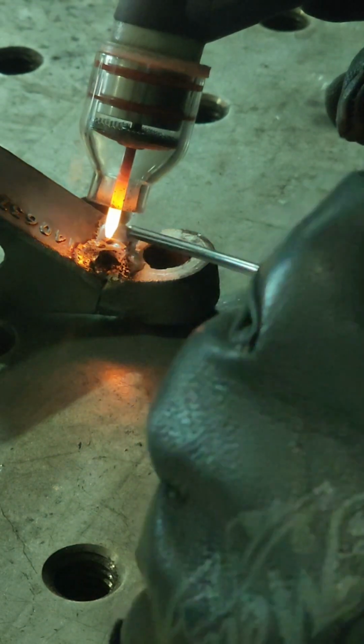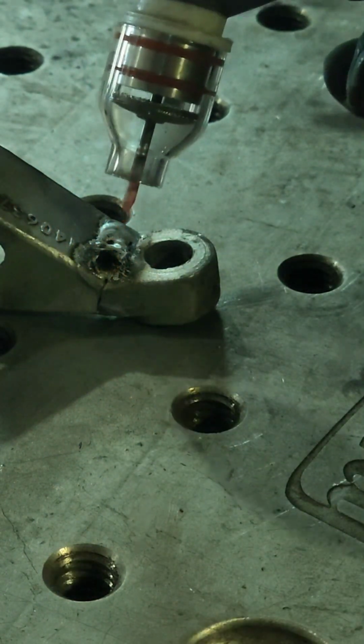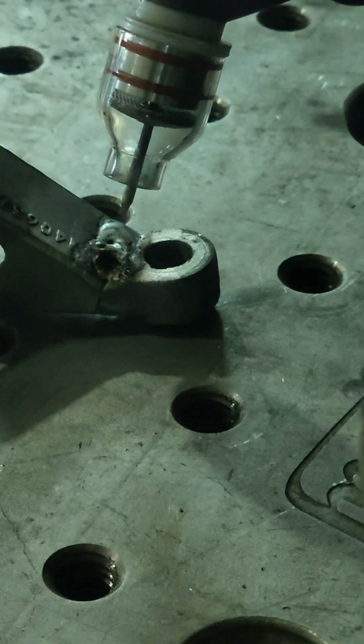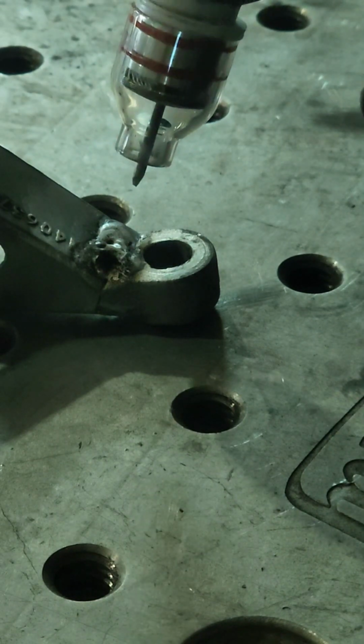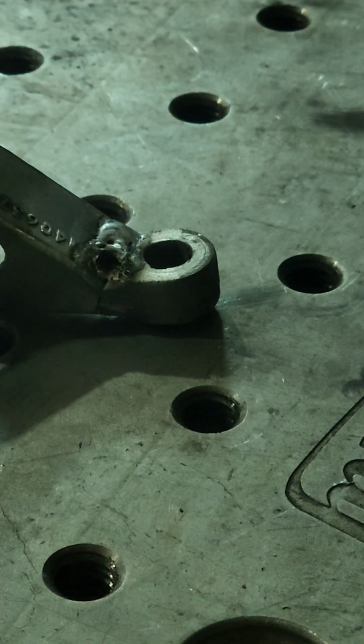You're going to keep your arc length, I'd say, about 1/8 of an inch off the material. You want to make sure both pieces of parent material are melted before you start to dab. Got a nice puddle established. You're going to see that black soot coming out of it. Like I said, I cleaned it up the best I could, and it's still really nasty. You can see that, even after I cooked it off and cleaned it with the wire wheel.